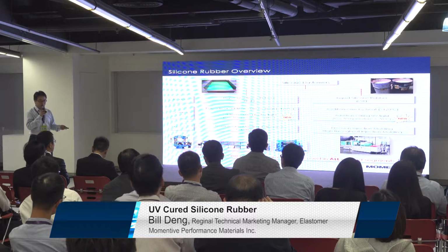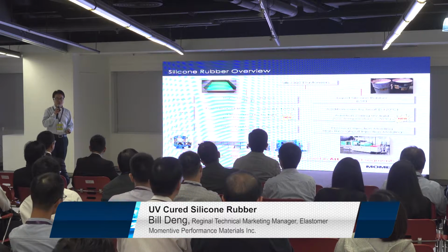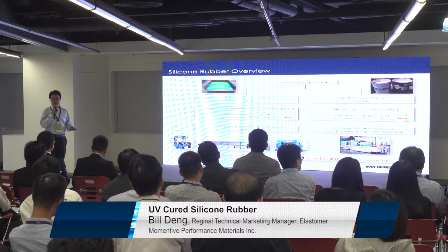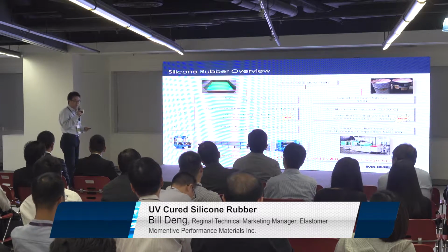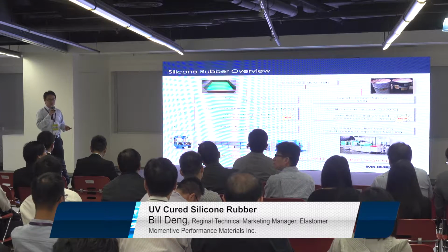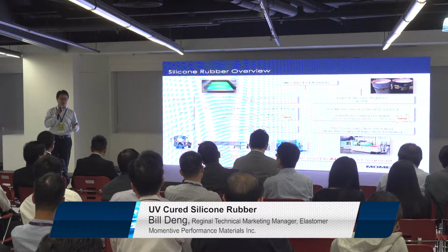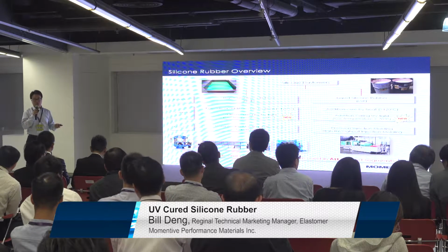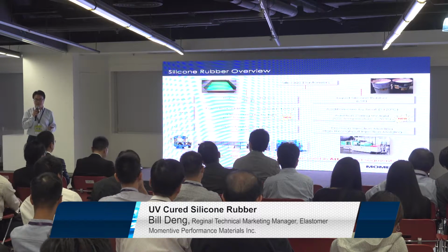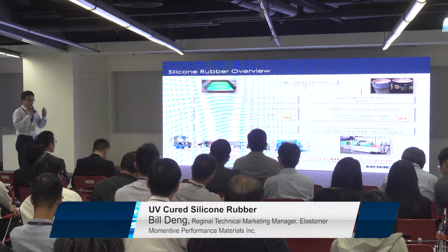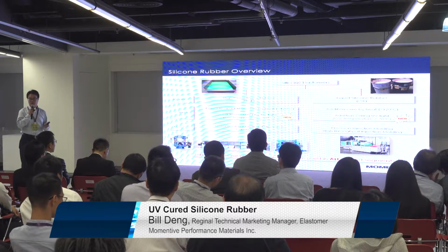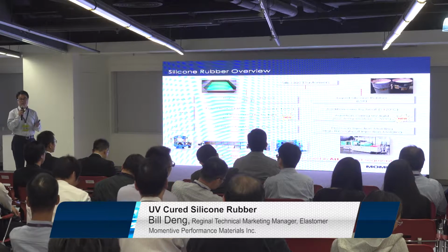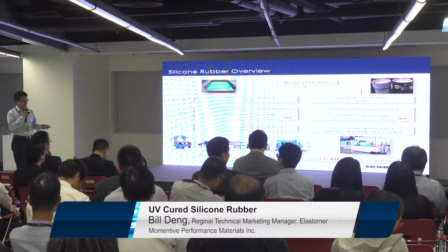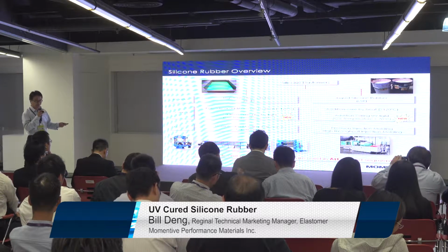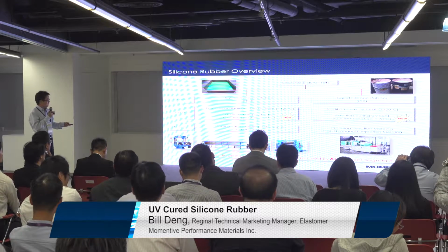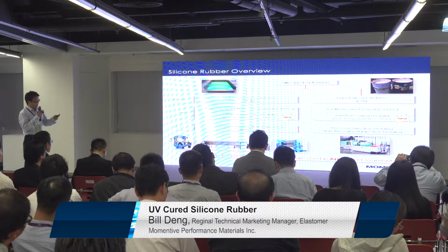In that way, if we look at current industry requirements, you will find a lot of applications like high-end consumer wearable devices and medical parts, like masks, because a lot of areas require silicone rubber to combine with plastic or other things like electronic devices. But if we apply high temperature, it will destroy the plastic or the electronic device. That's why how to make silicone rubber cured or processed at a relatively low temperature is of great interest to the industrial area. So that's why we developed the UV cured silicone elastomer product. We have both UV cured HCR and LSR. I will present it later.